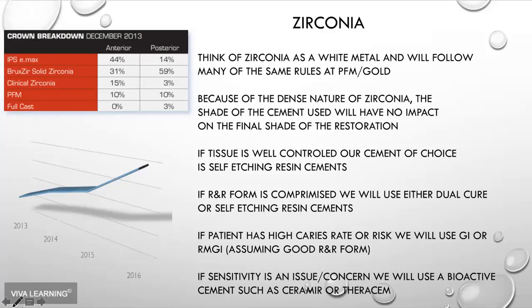So as far as cement selection, if your tissues are really well controlled, frequently my cement of choice is a self-etch resin cement. If I've got good retention and resistance form and the tissue's good and healthy, no reason not to use a self-etch resin cement. You've got good bond strength, you are going to bond to your zirconia, you will bond to the tooth structure, you will increase the retention of your crown with the cement because of the chemical and mechanical bond formed with the self-etching resin cement.